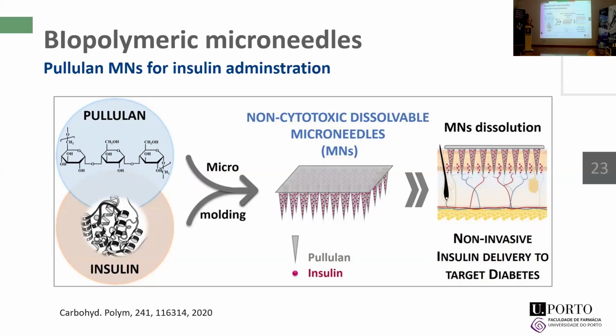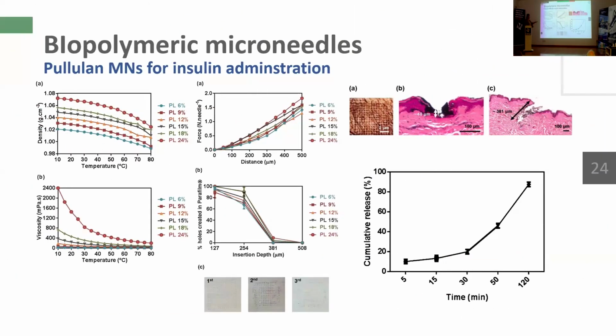This study involves, first of all, the optimization of the concentration of the solution, the adjustment of its viscosity to guarantee that we were able to fill the cavities of the molds. And then, of course, all the characterization to confirm that we are able to really perforate the stratum corneum and reach the desired skin layers. In this case, we tested the incorporation and release of insulin, for example for the treatment of diabetes. This work was more conceptual in terms of the valorization of this microbial polysaccharide.